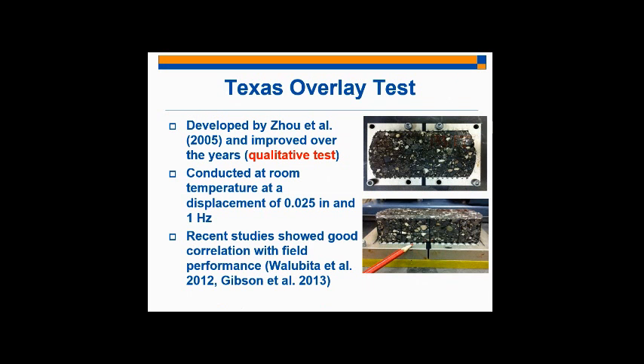And I mentioned correlation to an independent test. The correlation of our flexibility index test to an independent test. And so we selected the Texas overlay test for that correlation. Texas overlay was developed by Zhou, and it's a qualitative test. It's conducted at room temperature, 25 degrees Celsius, like our proposed SCB, at a displacement of 0.025 inches and 1 hertz loading frequency.